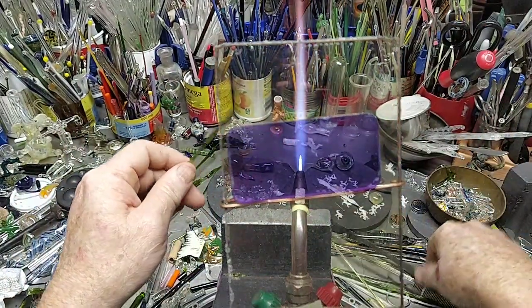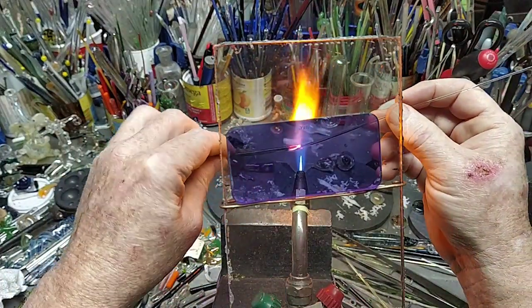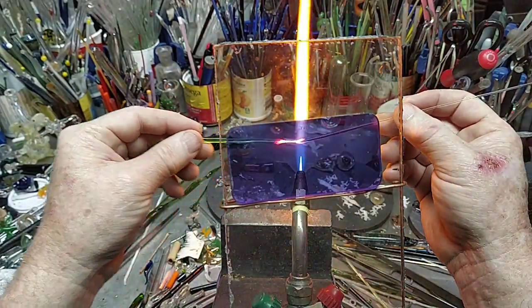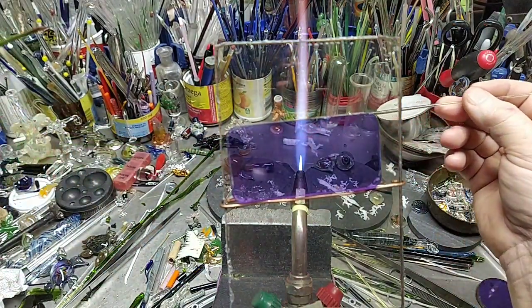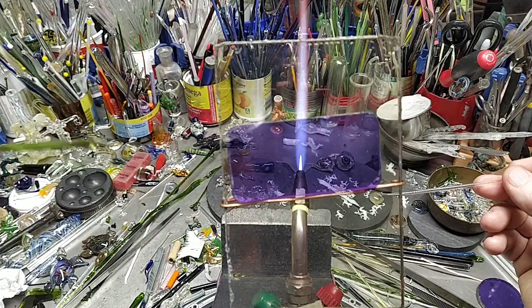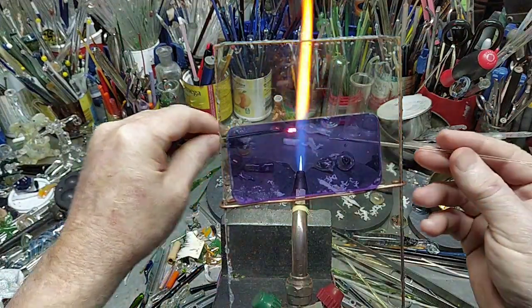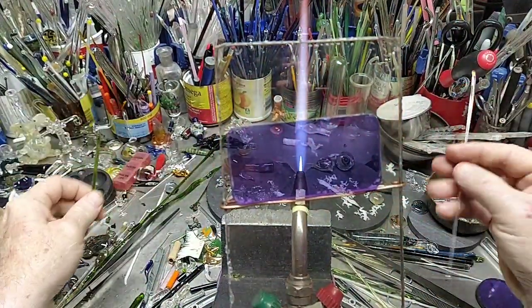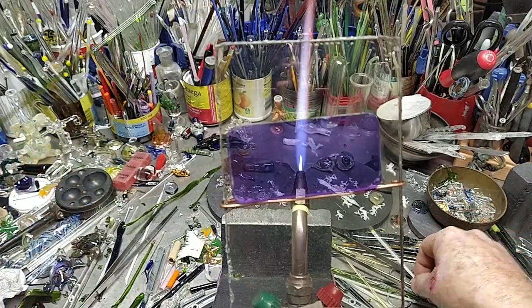We're going to go ahead and do that test one more time and try to do it a little bit thinner this time. This is where you find out whether two types of glass are compatible. Oh yeah, this one's going to really curve. See there, it's already starting. Look at that one. And I did that straight, and what happened? It went twang. That's when you know that two pieces of glass are incompatible with each other. And if you stick them together, eventually it's going to break apart right where they stick together, because they just don't work together.